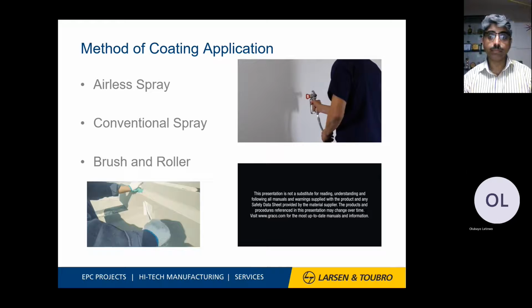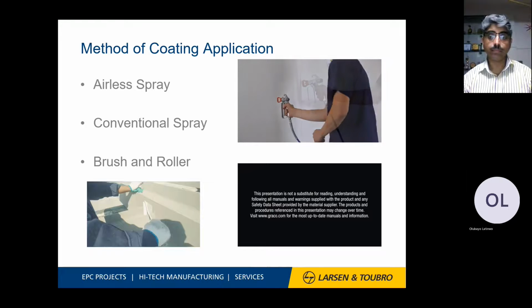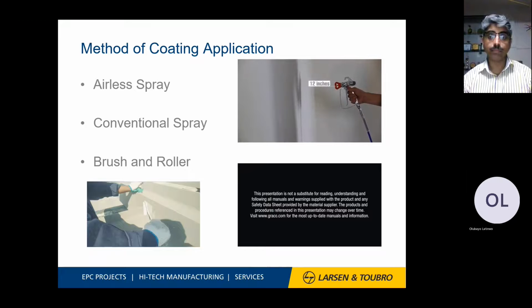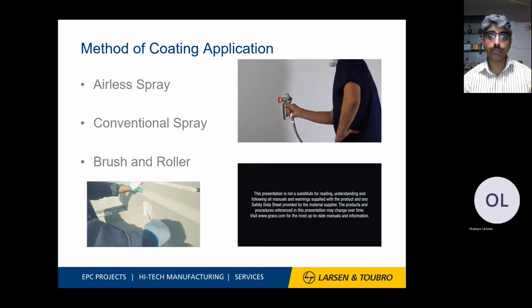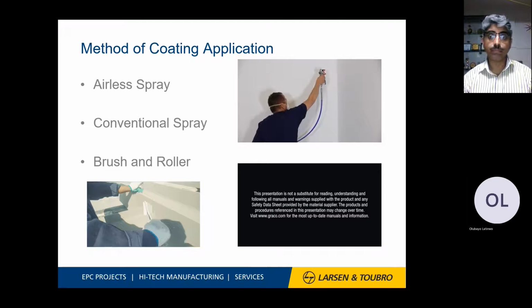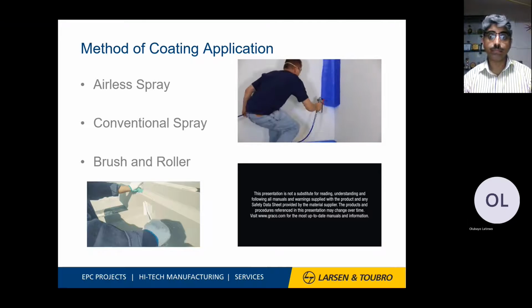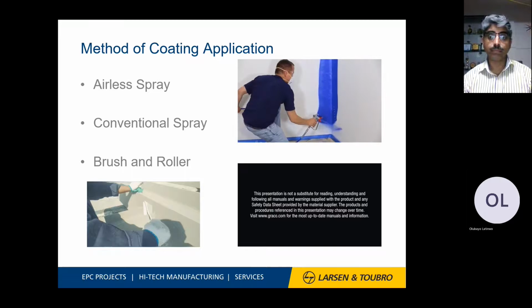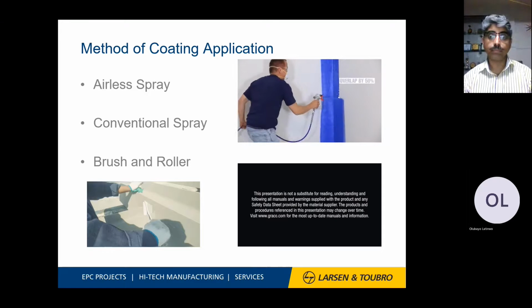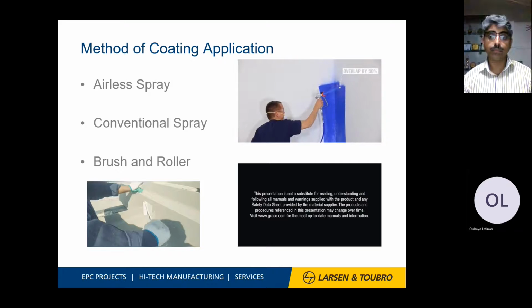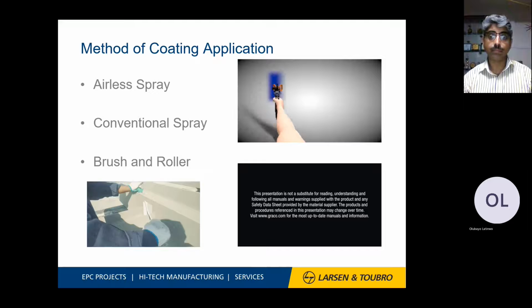Notice how at the beginning and end of each stroke, you'll flex your wrist to keep the gun square to the surface. Move out to 12 inches for additional practice. Work in sections only as far as you can comfortably reach. First, spray the outer edges and cut in any corners. Then, aim the gun at the edge of the previous spray pass so the spray pattern is actually overlapping each pass by 1/2. Trigger the gun after starting each spray pass and release before ending the spray pass.